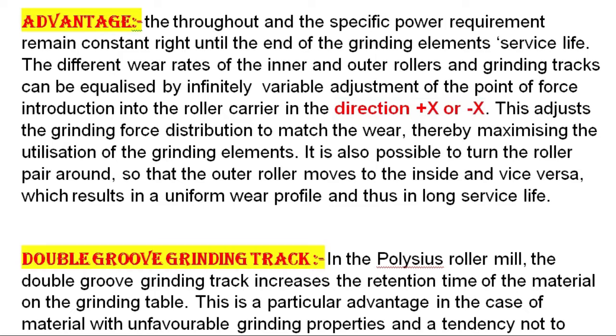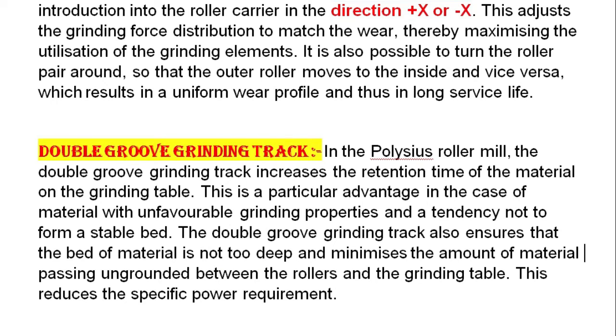The different wear rates of inner and outer rollers and grinding tracks can be equalized by infinitely variable adjustment of the point of force introduction into the roller carrier in the direction plus x or minus x. You can see in the picture this point. This adjusts the grinding force distribution to match the wear, thereby maximizing the utilization of grinding elements. It is also possible to turn the roller pair around so that the outer roller moves to the inside and vice versa, which results in a uniform wear profile and thus in long service life.